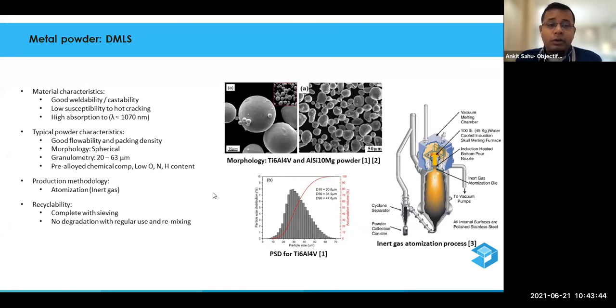So if you are trying to choose a new development alloy, then it should have good weldability and good castability. It should be a weldable alloy, a castable alloy, and it should not be susceptible to hot cracking. That is very much required because additive manufacturing is a kind of welding process. It should have a higher absorption of the laser, so the lambda should be higher than 1070 nanometer.